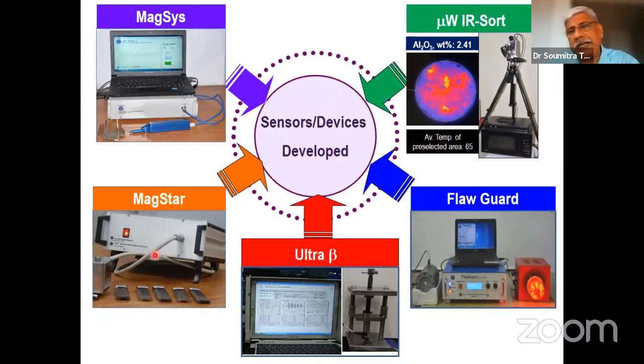These two, the MagSys and the MagStar, were non-destructive tools based on the magnetic hysteresis loop and the magnetic Barkhausen noise, through which the degeneration of a microstructure when it is in service can be quantified. Because that becomes a very important input whenever you are trying to decide if the component is safe or if the component can be reused. So these two, the MagSys and the MagStar, are based on magnetic principles, particularly magnetic hysteresis loop and magnetic Barkhausen noise. And these two devices that were developed by us, the technology was transferred to manufacturing units, and these have been commercialized and are in service.